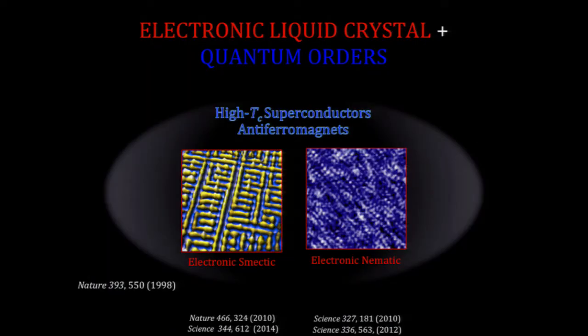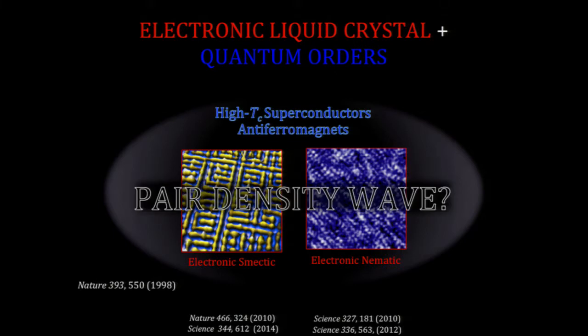So in STM, electronic smectics have been observed, as well as electronic nematics. This is in the cuprates. This is in the iron-based compounds. So we know that they're there. They're very strong. But now if you take these orders, which in some sense are classical orders, you're breaking point group symmetries, and then you combine them with quantum orders, such as magnetism and superconductivity, you can give rise to some kind of new order, which, for example, would be a pair density wave. The question is, what is a pair density wave?